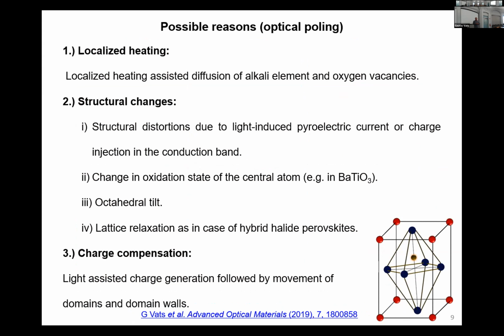There could be structural changes. So if you imagine the structure, there could be an octahedral tilt, there could be a change in oxidation state of the central atom, there could be a lattice relaxation. Third possibility is charge compensation. So the idea is when you shine light on the surface of the material, it generates charges on the surface, which are compensated by the movement of ferroelectric domains. Let's look at these possibilities one by one.